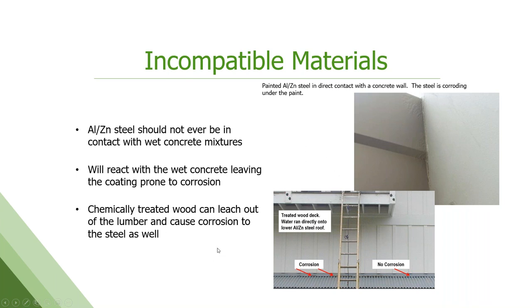And then wood, treated wood. Wood is often treated with copper compounds, which are really not compatible with painted metal. So if you have a situation where a wood deck or some kind of wood framing is in direct contact or can leach water onto the painted metal, you're going to get corrosion. So this is a house in Hawaii. The corrosion was only occurring under this wood deck right here. As soon as you got past the edge of this wood deck, the metal was fine. And it had to do with the treatment that was leaching out of the deck above it.